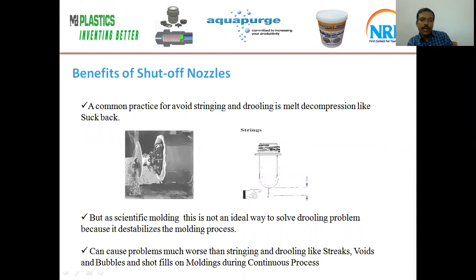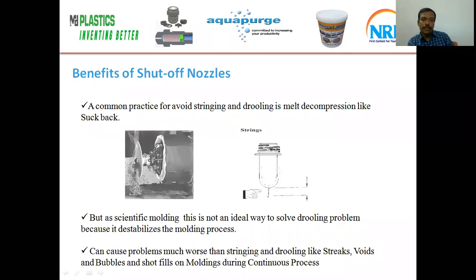See, a common practice to avoid stringing and drooling in moldings is to increase suckback. But in scientific molding approaches, we should not use suckback for drooling or stringing because it will destabilize the molding and make drooling worse. So normally we have to use a shut-off nozzle to prevent stringing and drooling in the moldings. By using a shut-off nozzle, we can prevent streaks, voids, bubbles and short fills on the moldings. Also it helps process consistency and repeatability.